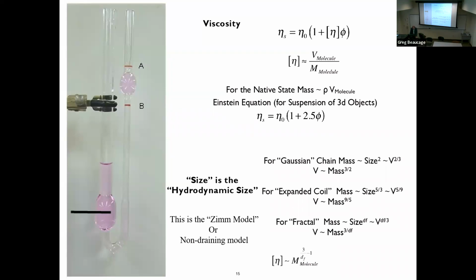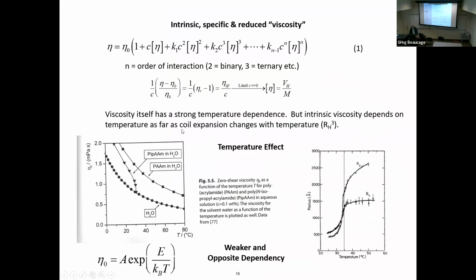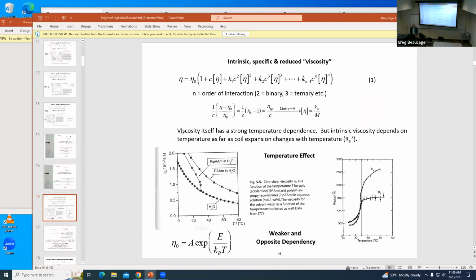So if you just say the intrinsic viscosity is K times molecular weight to the A, that's called the Mark-Houwink equation, which is Hermann Mark, the guy at Brooklyn Polytech, right? You can find the Mark-Houwink coefficients tabulated in the Polymer Handbook. Basically, you can find the A and K terms. You just Google it. The NIST web page has them too. So if you do that intrinsic viscosity measurement, you can get the molecular weight using the Mark-Houwink coefficients.